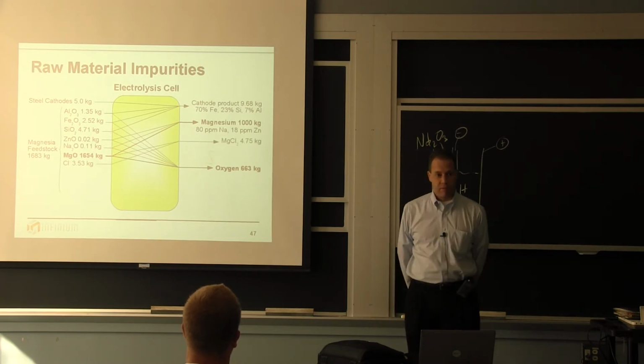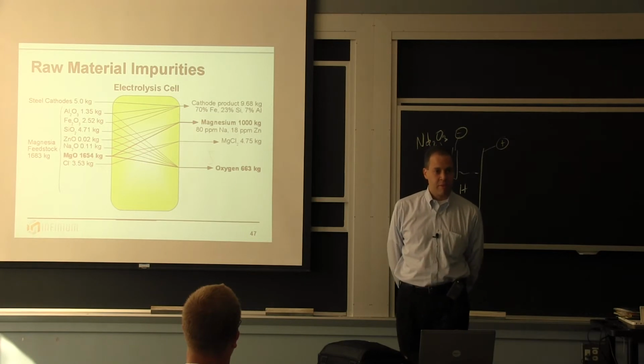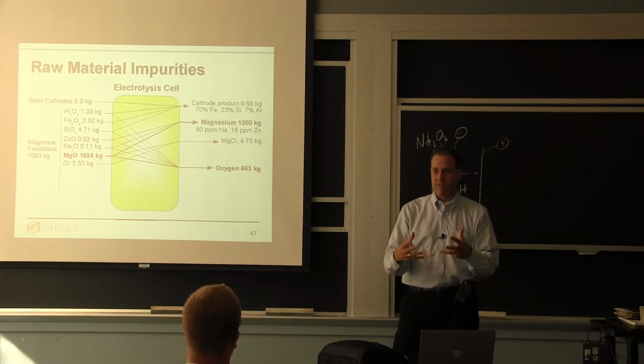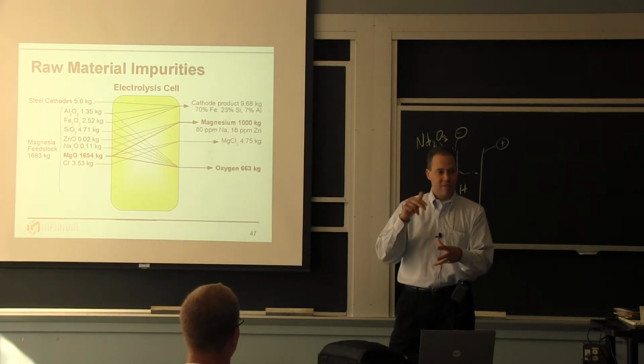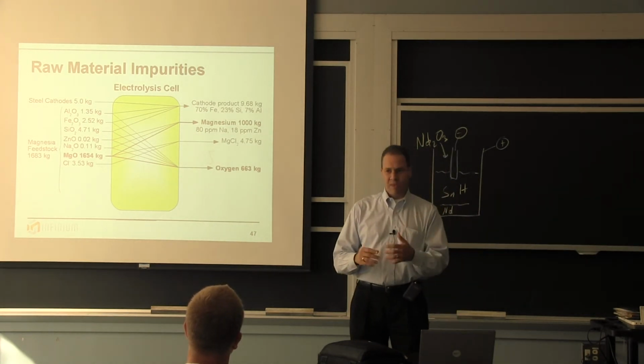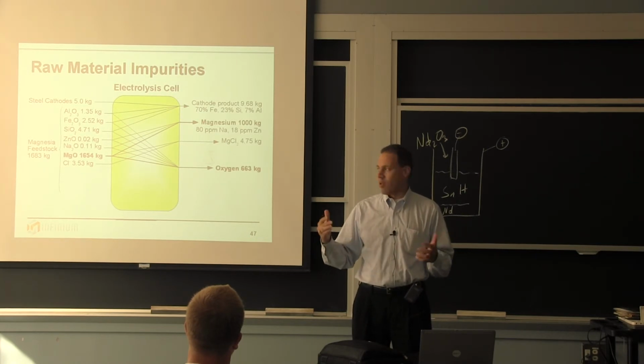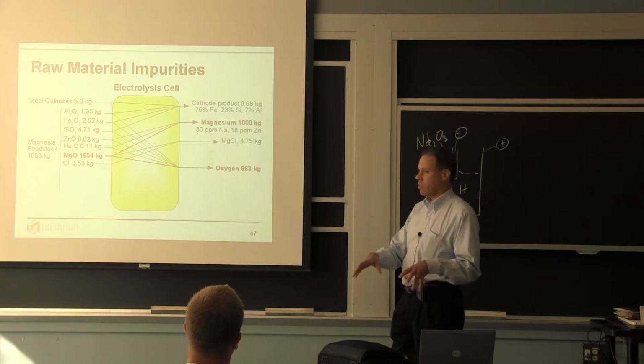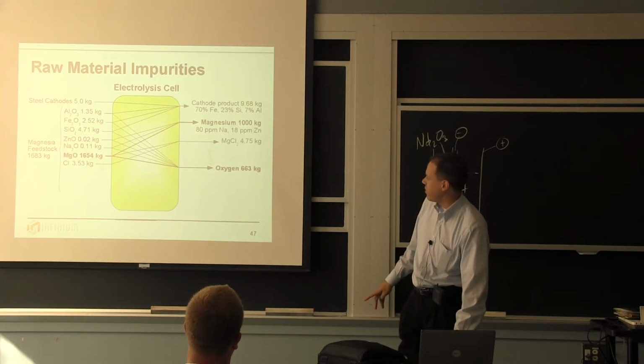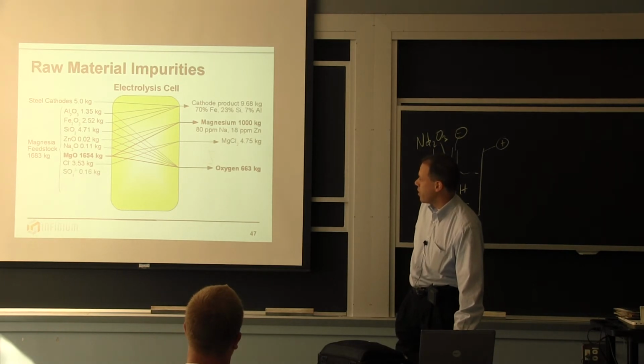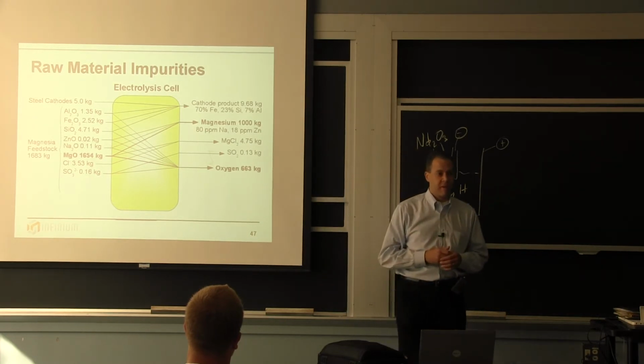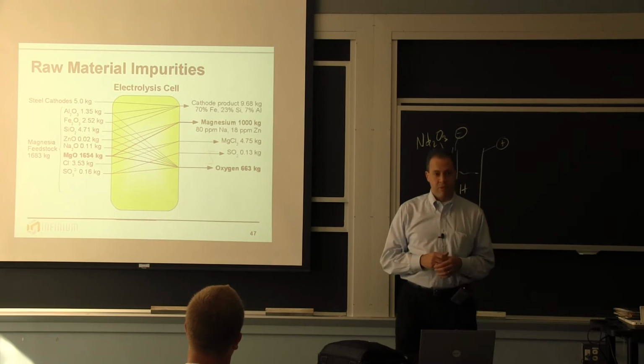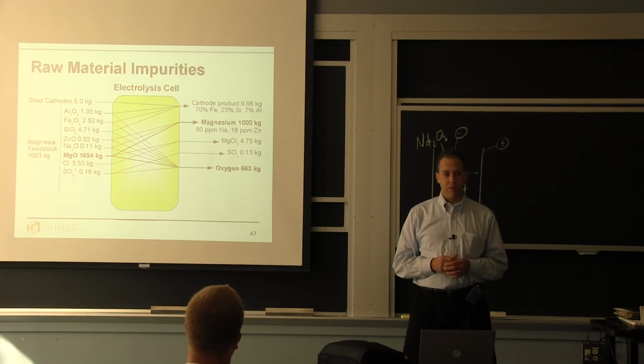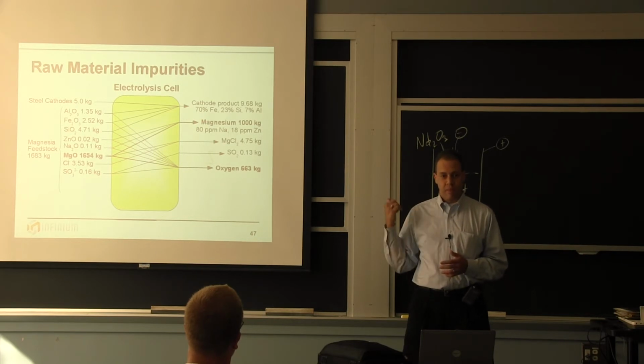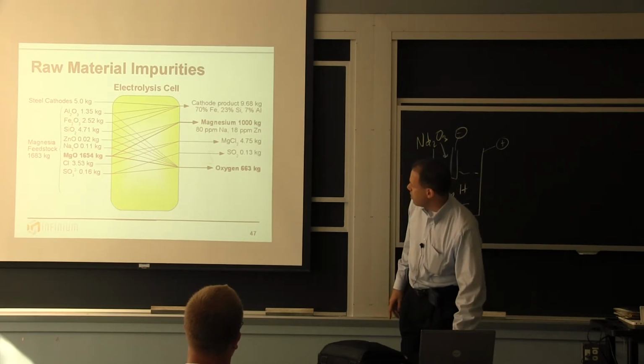So chlorides just evaporate at these temperatures very slowly, to the point where we end up with a steady state where it's built up in the crucible enough so that it's evaporating off at the same rate you're feeding it in. That gets into the condenser. We actually haven't seen it in the condenser yet because we haven't run for long enough, I guess. But about 5 kilograms will separate out, just density separate in the condenser, for every metric ton of magnesium. Sulfates are present in the raw material. That's our only emission in the course of heating the raw material. You get 100 to 200 grams of SO2 emission per ton of magnesium. So this is low enough that we should not need any permits.